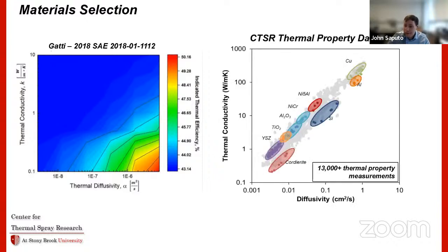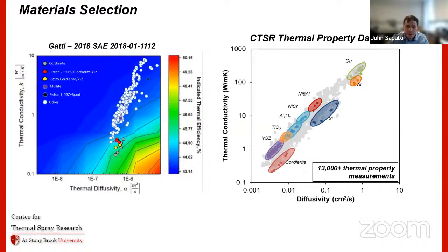So we're pretty lucky at the CTSR. Our lab has been around and measuring thermophysical properties of sprayed coatings for a long time. So I've got a list of about 13,000 measurements of actual sprayed coatings that we can look at. And you can take this same plot, conductivity versus diffusivity, and overlay that onto this guy's efficiency plot. You can see that there's a certain range down here that falls into this green category that's readily achievable thermophysical properties of a sort of traditional coating that we want to look at.